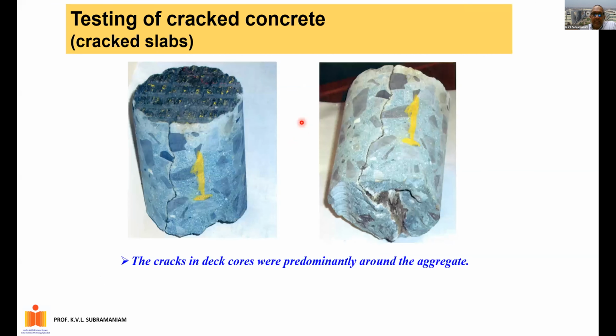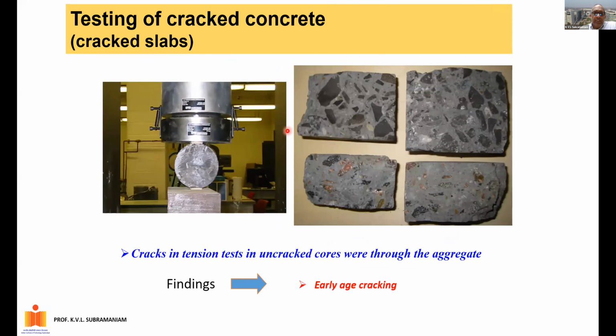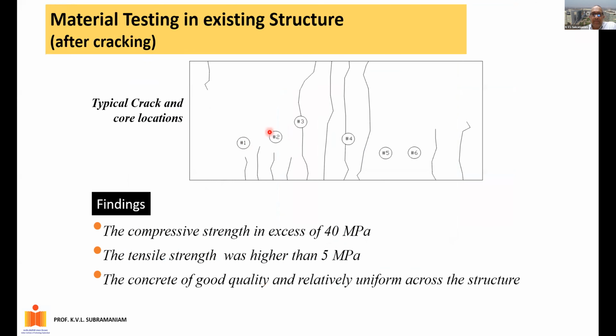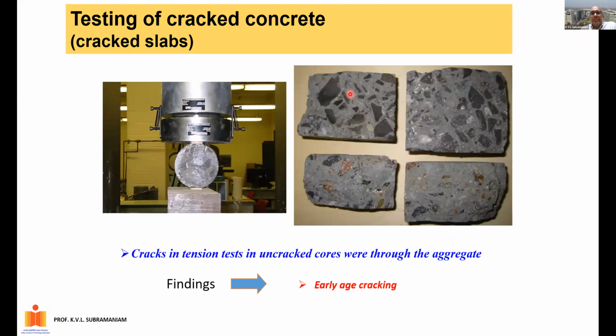It was found that in this core, if you see, the crack goes around the aggregate. So this is a crack that goes around the aggregate. So it was established that this crack was formed very early. This was basically a crack that formed within the first few days after casting. Because when we tested the core from a healthy part of the bridge deck, so this is the core that was taken from a healthy part of the bridge deck, if you test this core, basically all the aggregate was split.